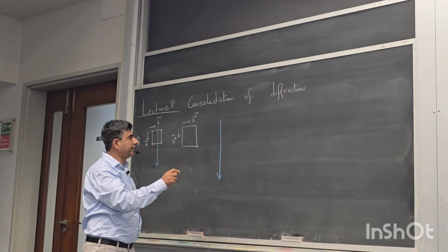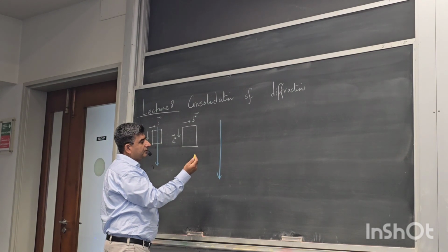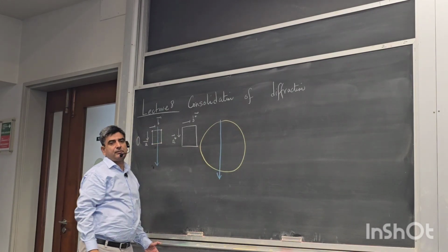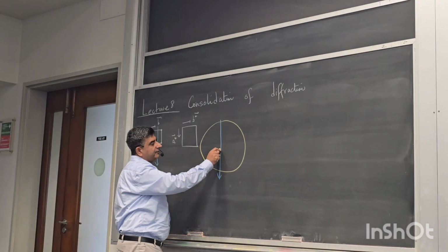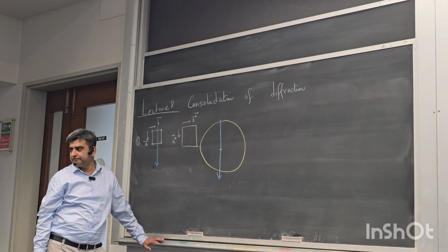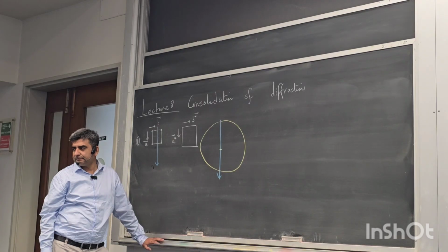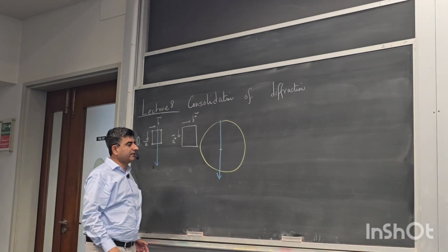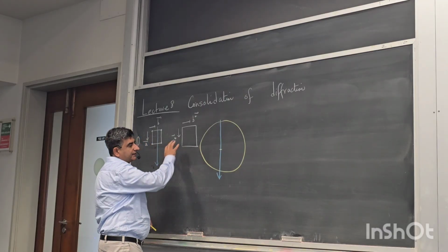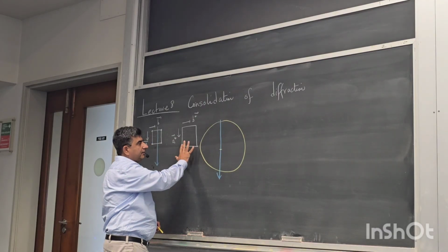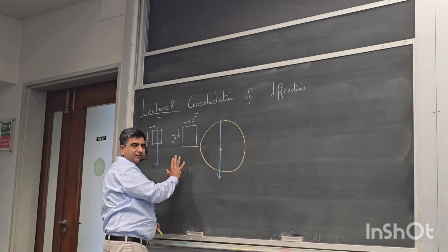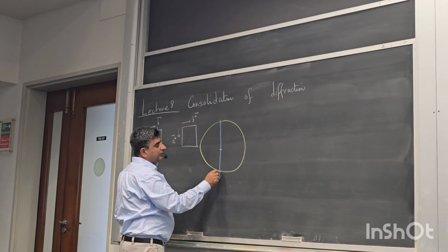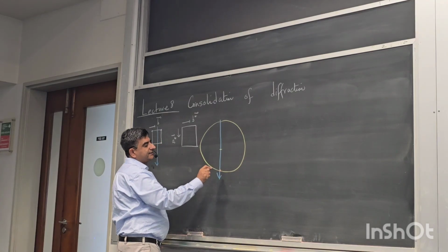What you would really like to do is start off by drawing a circle of radius 2 pi over lambda anywhere on your paper, and then you take your reciprocal lattice, and without turning it around, you position your reciprocal lattice so that one of the points coincides with the exit point of the circle.